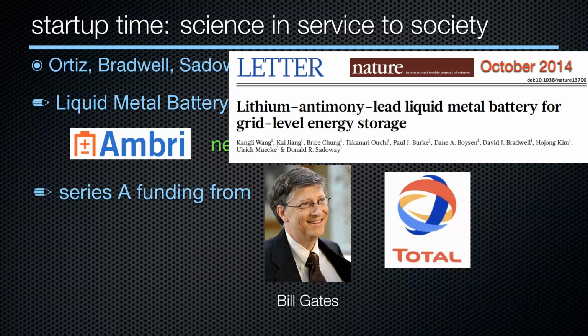And then along the way, as I told you, we used lithium for one electrode and antimony lead for the other electrode, and that too resulted in a paper in Nature. And with that paper in Nature, it was powerful in launching the careers for many of these young people. And what was going on there was the main discovery was that the lithium antimony was a high voltage system, but antimony melts at 630 degrees Celsius. And we wanted to get the operating temperature down.